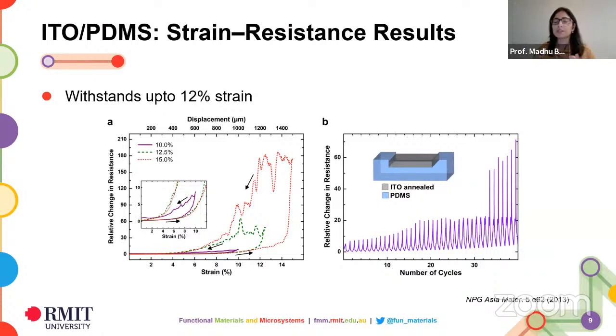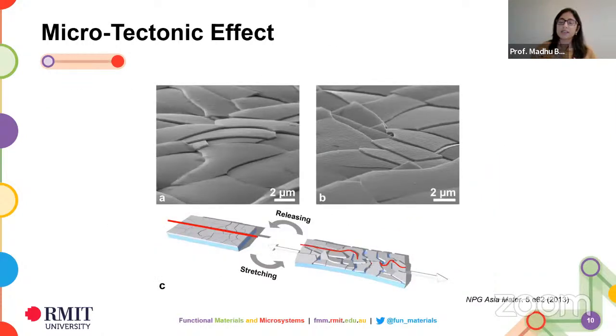But then after that, we improved on the recipe. You could get much more stretchability as you kept doing other materials. So we were quite fascinated, and we were trying to understand how is it that an oxide layer, which typically cracks and is brittle at 2 or 3% of strain, is actually able to withstand much higher strain limits. And when we looked at the indium tin oxide material under a microscope, we realized it's no longer just a continuous thin film. What you almost have now are kind of plates.